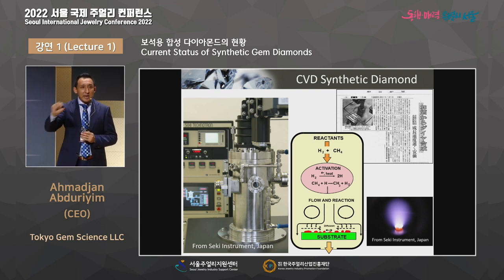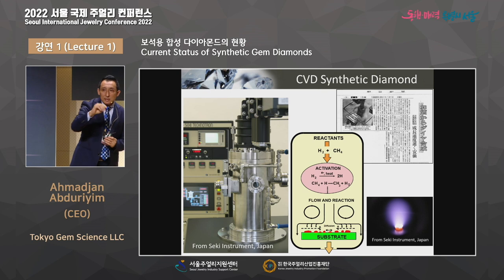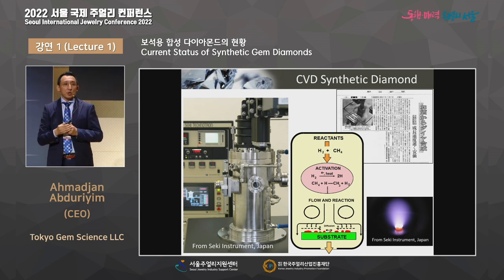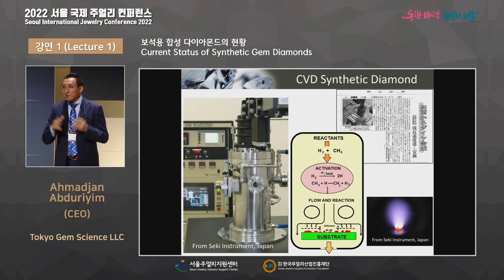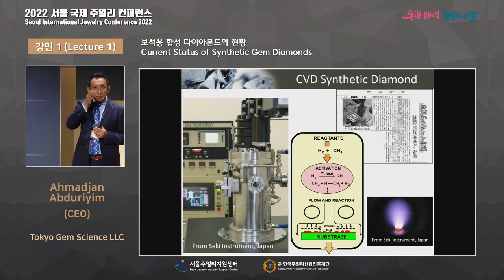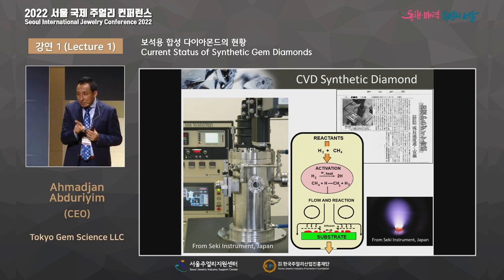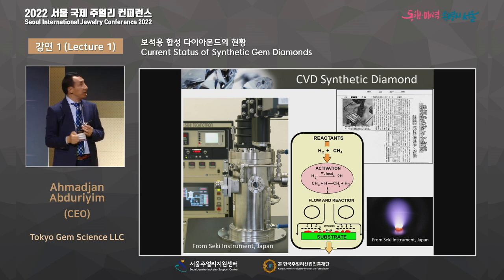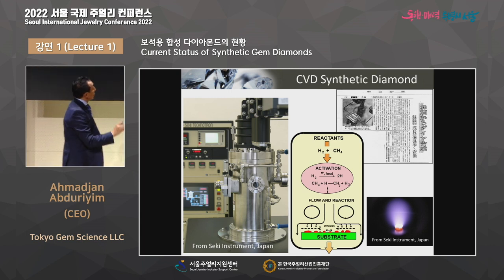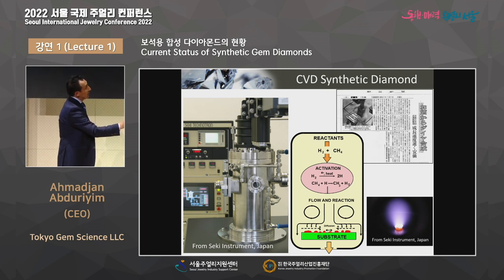For the film, they never create a single crystal. They just make a film. This film can be used in optical instruments like FTIR, like an infrared beam splitter. That is a used CVD diamond film. So looking at the inside, we see the hydrogen and the methane gas can be made active to react to each other. And methane can become methylene at a lower temperature. And the carbon can drop on top of the seed.